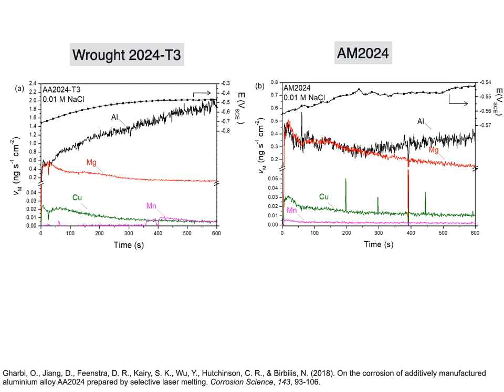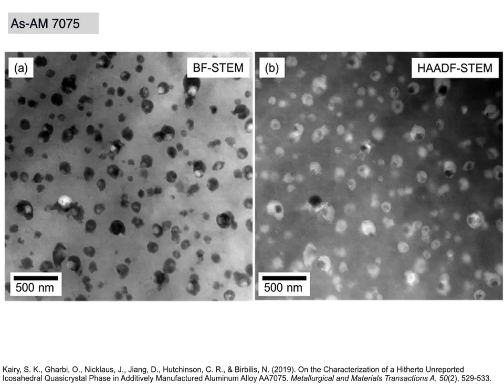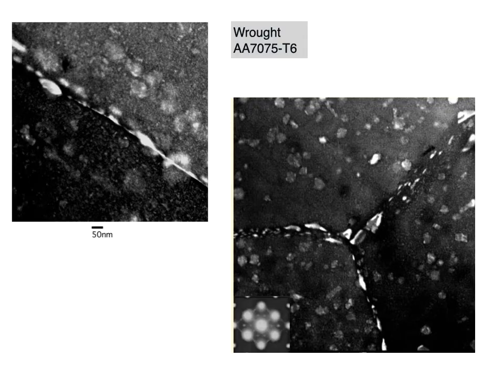And look, I'm not going to elaborate here because a deep dive into this work is actually on YouTube from Umaima's presentation at the last ICAA meeting. But I think that's an important example so that we can also start to see a body of evidence emerging. So since then, a similar story rings true for the aluminium zinc magnesium alloy 7075. What we see here when produced by additive manufacturing is a very different nanostructure to the wrought alloy. And here you see the wrought alloy where you see eta precipitates, so MgZn2 precipitates.